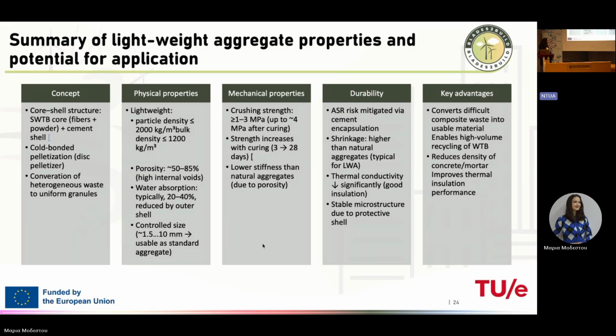So basically, this is a summary of what we get for lightweight properties. We have quite high porosity, from 50 to 85%, with internal voids. We have encapsulation of this waste covered with cement. We had thermal conductivity, I didn't include this data, but it is quite low, so it can also be good insulation. It has a stable microstructure due to this protective shell.